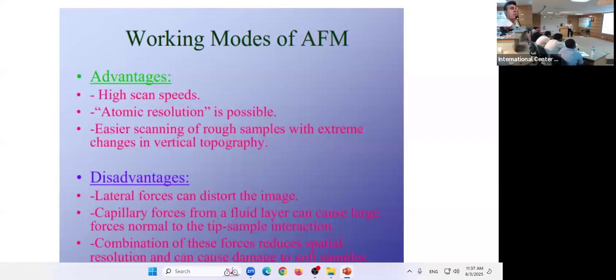The scan speed is also high. Here you can set a high scan speed, but do not set a very high scan speed. Otherwise, you will contaminate your sample with a greater speed, and similarly, the greater the speed, the lower the resolution. If you want to get a better resolution image, always keep the speed low. That would give you much better resolution.